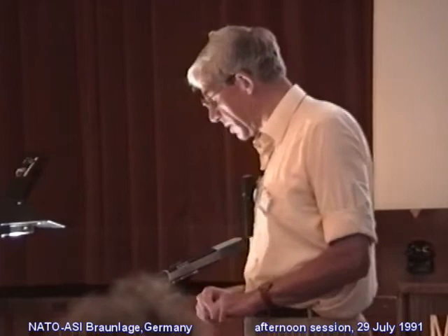In the normal linear elastic loading problem, there is no change in the area over which the loads are applied as you bring the two surfaces together. Here, initially they touch on a very small area, so they're very compliant, and they deform easily. As the area of contact increases, the compliance decreases and the stiffness increases, so that they behave like a stiffening spring, giving a deflection which is nonlinear with load, and a stress which is nonlinear with load.